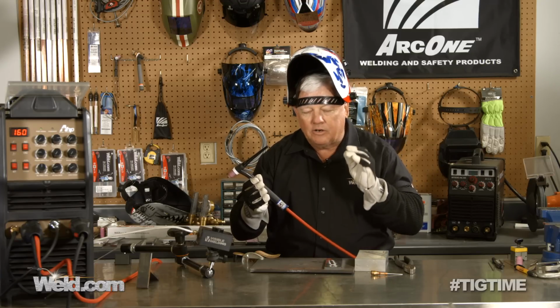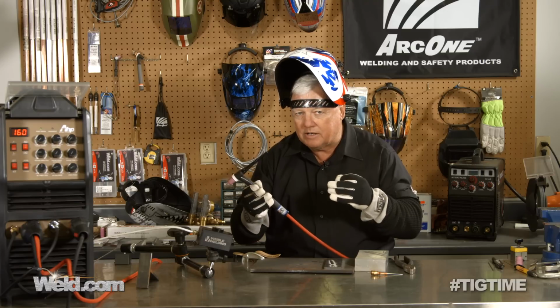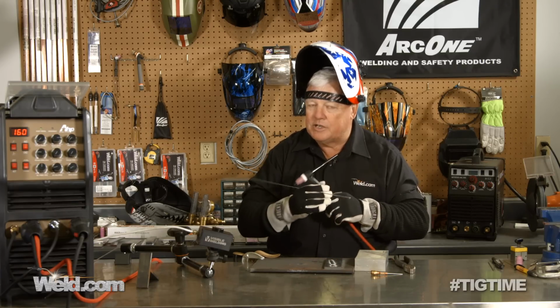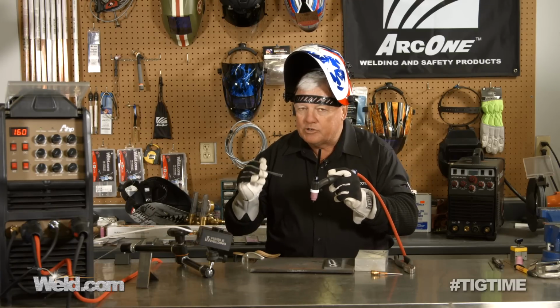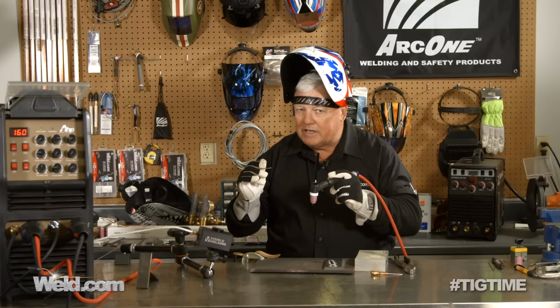The one thing I caution you on is that hot short cracking can be prevented just by adding filler material. There's a secret to that also. When you start your puddle, make sure you dab just a little bit of filler before you have any travel speed whatsoever. So I'm going to go ahead and simulate that right now. Okay, I'm just going to wait till I see a puddle. It's actually a little more difficult to fuse. Seems to be running nice and clean. Good cleaning action.